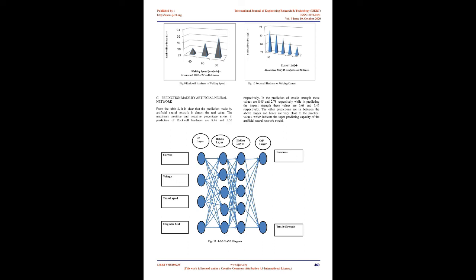If the speed of welding was increased from 40 mm/min to 80 mm/min, the hardness increased from 90 RHB to 92 RHB. If the voltage was increased from 20 V to 24 V, the hardness decreased from 89 RHB to 85 RHB. If the current was increased from 90 A to 110 A, the hardness decreased from 88 RHB to 80 RHB. The variation of hardness properties with magnetic field, voltage, welding speed, and current were shown in figures 7, 8, 9 and 10 respectively.